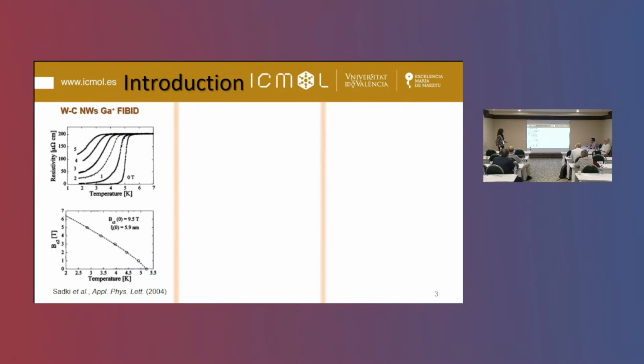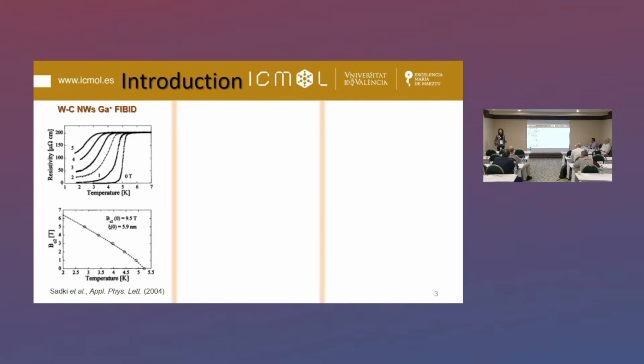In 2004, Sadki and co-workers reported that these tungsten carbon nanowires grown using Ga+ FIB presented superconducting properties below 5 Kelvin. It's a type 2 superconductor, s-wave, and the upper critical magnetic field was around 9.5 Tesla, and the superconducting coherence length around 6 nanometers.